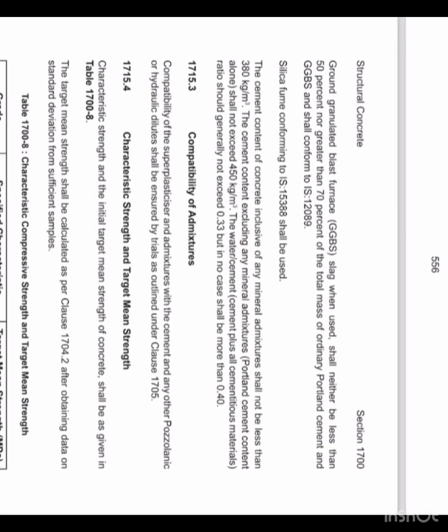Silica fume conforming to IS 15388 shall be used. The cement content of concrete, inclusive of any mineral admixture, shall not be less than 380 kg per m3. The cement content, excluding any mineral admixture, that is Portland cement content alone, shall not exceed 450 kg per m3. The water to cement plus all cementitious materials ratio should generally not exceed 0.33, but in no case shall be more than 0.4.